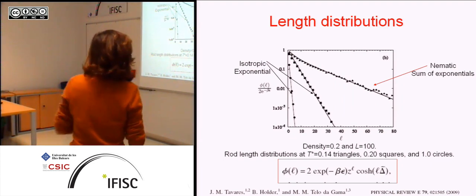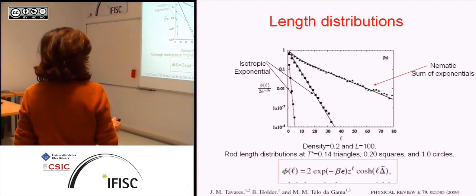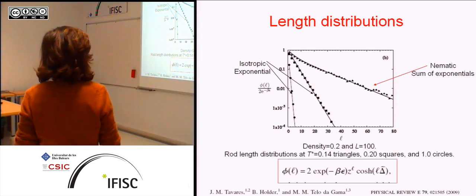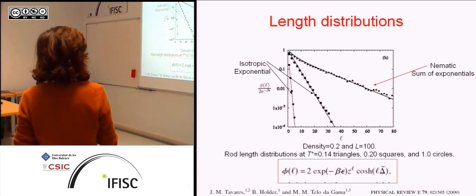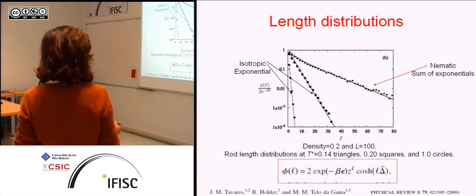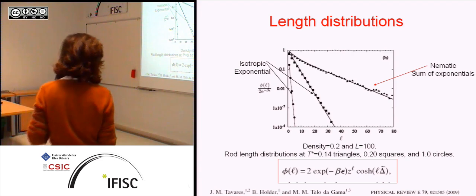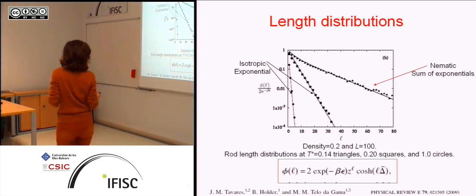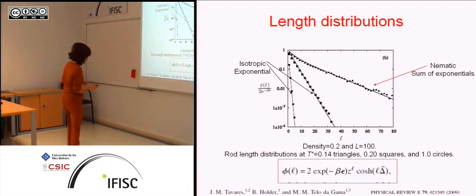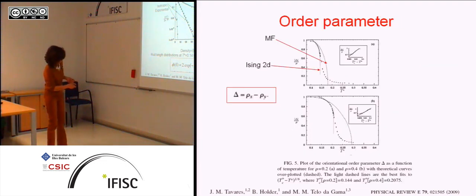And well, the length distributions are exponential. There are two exponentials in the ordered phase and only one in the isotropic phase. The lines again are this mean field theory that I will not bother you with, and the dots are from the simulation. On this scale again, the agreement seems to be perfect, as good as you expect. And these are the expressions actually for the length distributions.